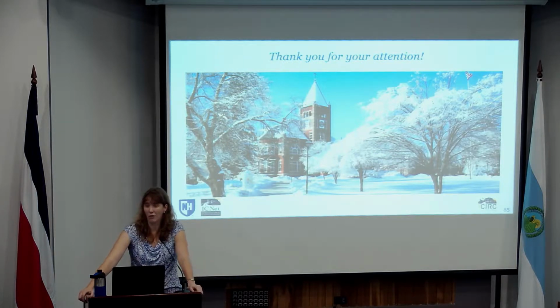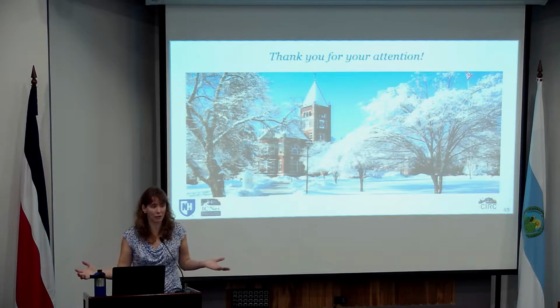In terms of looking at the different temperatures, based on what we've seen, it looks like there's definitely differences in those aging temperatures, and we're reserving judgment on which one is better until we get some more of the field data. Because there's the difference, again, for viscoelastic characterization, you can do either one. But when you're looking at the fracture characterization, we want to make sure we're really representing what's happening in the field. And right now, that's an open question, because we just don't have enough of the field data, the actual field aging results, to be able to make that assessment.